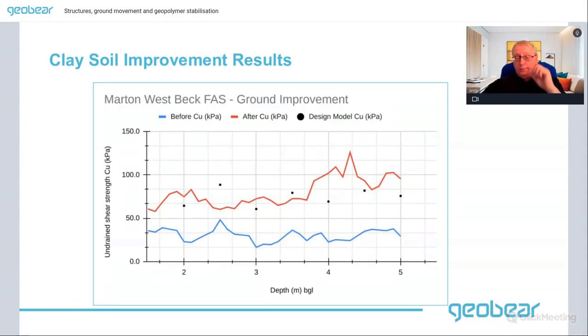And here's an example from one particular case that we've looked at, where we had a very soft clay on this site, and the blue line was the undrained shear strength before the injections, and the red line is the undrained shear strength after the injections, and there's around about a 250% improvement. And the black dots on the graph is our model prediction as to what performance we would get. And essentially, we use a model to calculate how much polymer we need to put in, what type of polymer, and the spacings of the injections in order to get to a desired outcome. And there's a good result here. And we have many case examples where our predictions turn out to be correct.